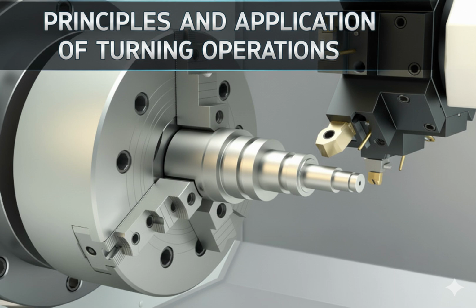This leads us to a big choice. Positive versus negative inserts. What's the trade-off? It's all about strength versus cutting force. A negative insert has a strong 90-degree wedge angle. It's a tank. It can handle heavy cuts and interruptions, but it requires more force to push through the material. A positive insert has a sharper angle, less than 90 degrees. So it slices more easily. Much lower cutting force. It's perfect for those sticky ISO-S materials where you want to minimize heat, or for machining long, skinny parts where you can't have a lot of tool pressure causing vibration. So you give up some edge strength for a cleaner, gentler cut. That's the trade-off. Strength versus vibration.